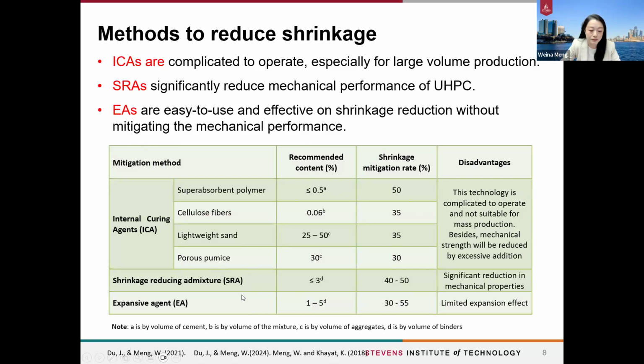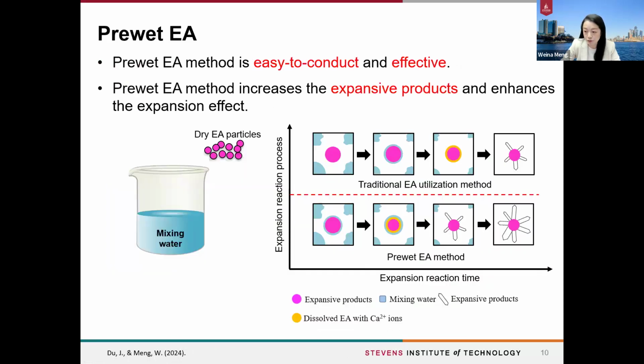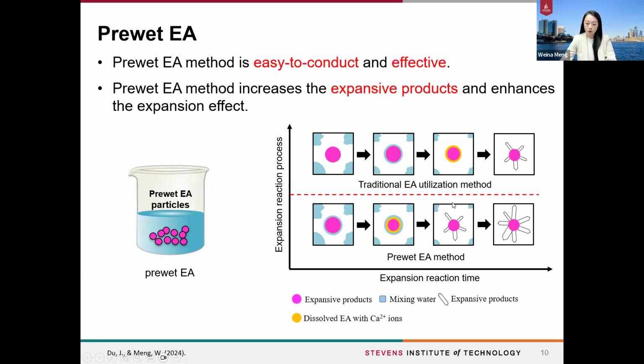So in our study, we try to further improve the efficiency of the expansive agents to improve the expansion effect for reducing more shrinkage. So we simply add the dry expansive agents into water for a couple of minutes to allow sufficient water and space for it to grow more expansive products, so as to enhance the expansion effect.